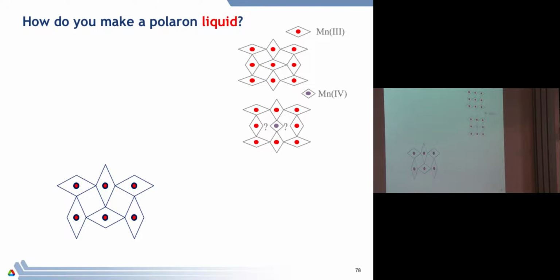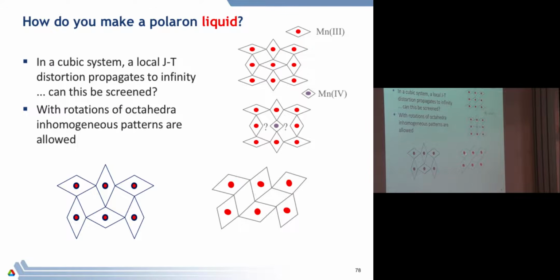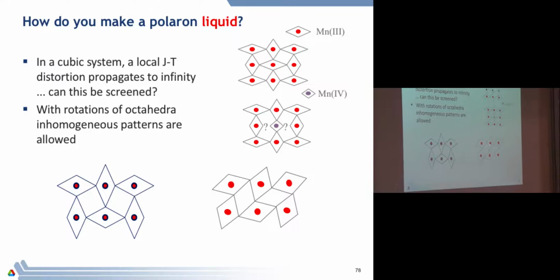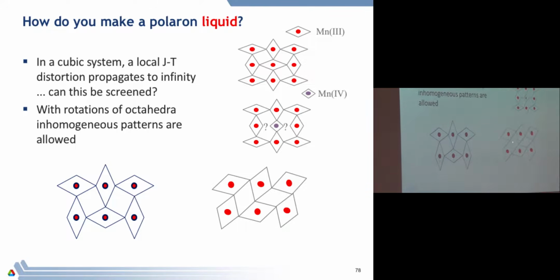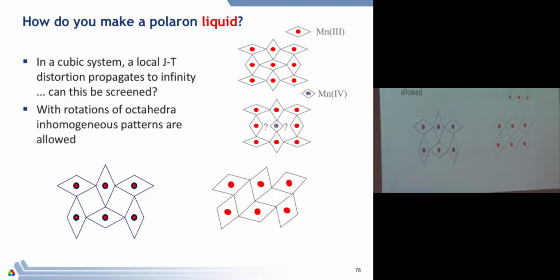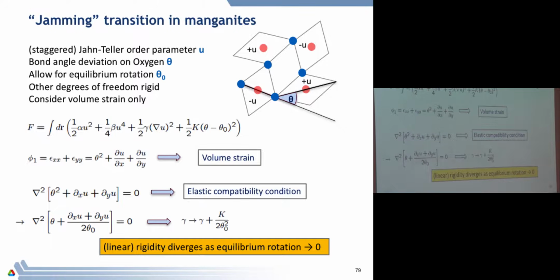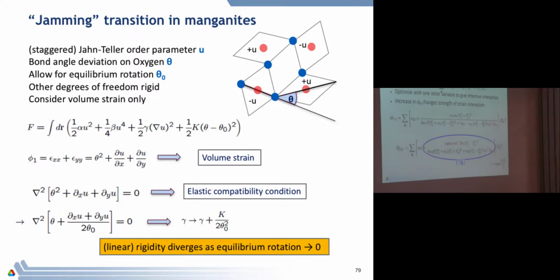Well, intuitively there really is, because suppose that the ground state didn't have everything perfectly aligned along these axes. Suppose it actually had some rotations built in. With those rotations built in, you can intuitively feel that if I change the shape of here, instead of forcing the neighbor to change its shape, it could rotate instead. And the amount that it rotates depends on the other ion, which I haven't even shown here, which is holding the structure up. So this is an inherently softer structure than this one is, and therefore it's easier to disorder. You can actually make a theory about that, and since I'm running out of time, I'll make you read the paper.